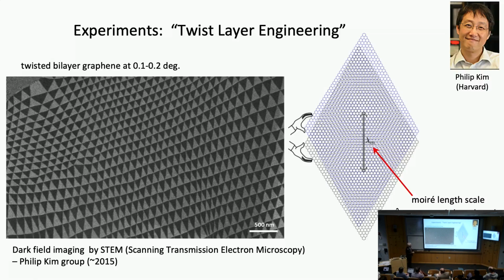By the way, you should notice even from this picture a basic difference between a simple-minded Moiré pattern obtained by simply putting one layer on top of the other and what is actually seen experimentally, which is this very nice pattern of upward and downward pointing triangles, lighter and darker in shade, in this scanning transmission electron microscopy experiment. I'll revisit that and explain the origin of this. I think it's a crucial aspect of how the system behaves. So we now basically have an adjustable superlattice parameter to control the electronic behavior, essentially at will.